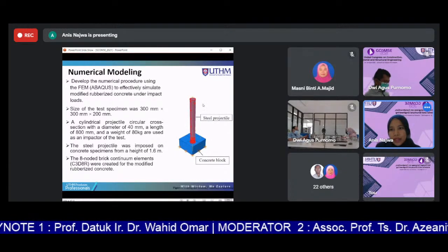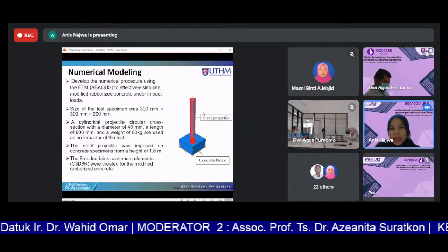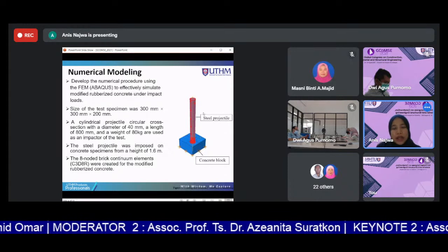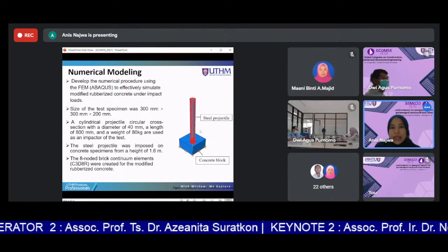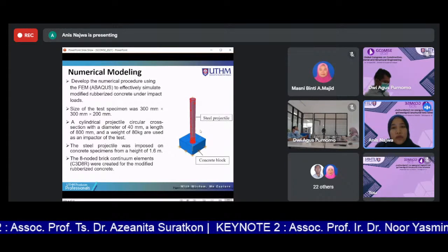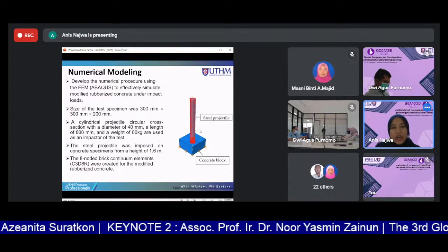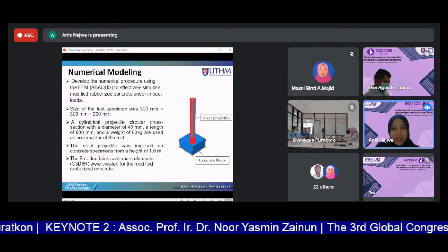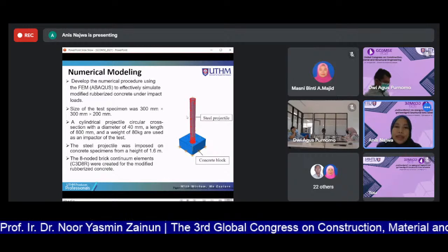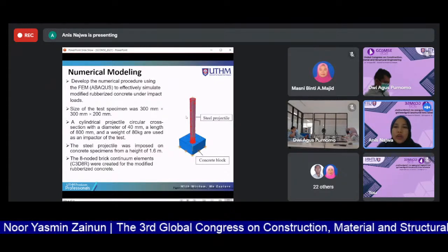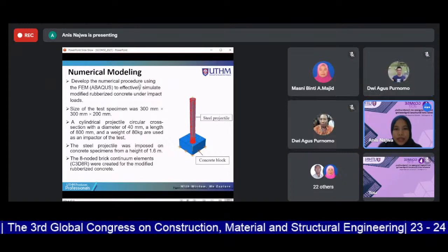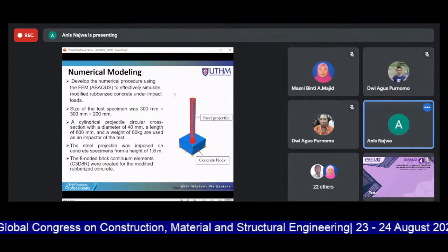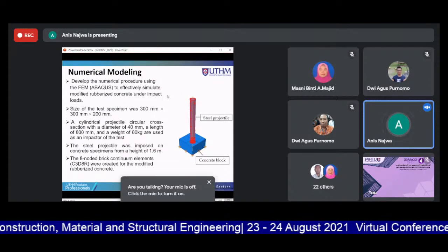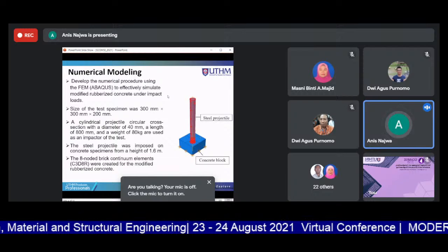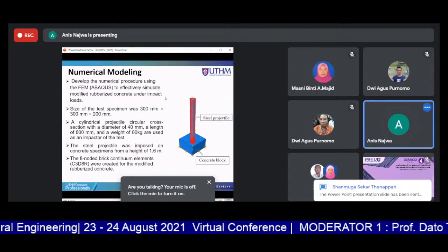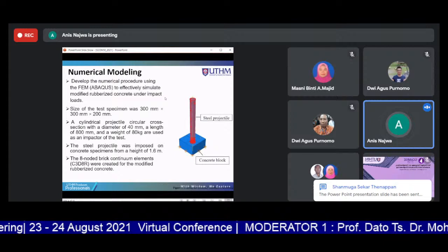And up here is a steel projectile, which is free falling from about 1.6 meters high. The size is about 40 mm in diameter and the length is 800 mm, and the weight is about 80 kg, as in the free falling test. Then the 8-node brick continuum elements were created for this modified rubberized concrete in the Abaqus software. And the velocity is about 4 meters per second, as in the experiment. Then for the software, it keeps on increasing to 5 meters per second and 6 meters per second.